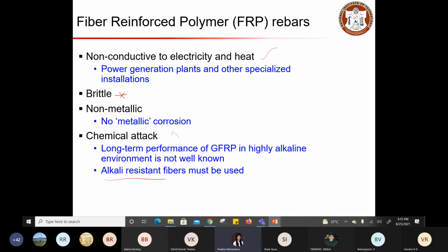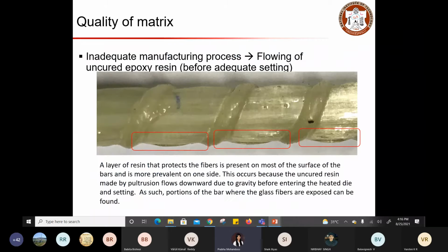So this comes under the negative part. These basically represent the advantages of your rebar, and then this brittleness and this chemical attack represent the disadvantages of your rebar. But you can account for this disadvantage by taking care at the design stage, where you limit the failure within the yield limit, then you can go with this. And when you check that your fibers are alkali resistant, then there will not be any issue to use this type of GFRP bars in a highly alkaline environment in concrete.